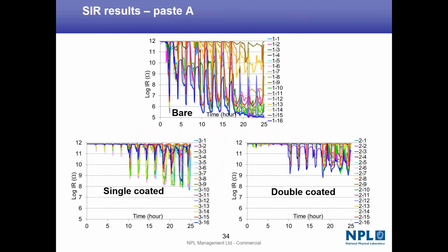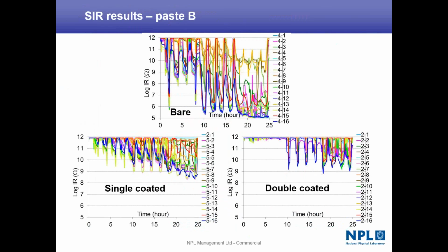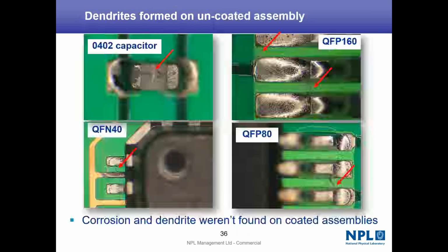So if you're familiar with insulation resistance measurement, we're seeing exactly the same, just interpreted or shown in a slightly different way. But you can see that a board has had a single coating of conformal coating, and then a board that's had a double coat, you can see how more protected, if you like, the surface of that printed circuit board has become. In this example, we're just moving on and just showing a paste B. Again, the emphasis here wasn't to look at the performance of the paste, it was to look at how the results would be shown on the different products or the surface conditions with different amounts of humidity.